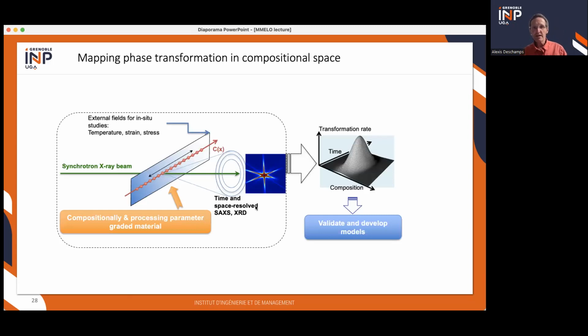The principle is very simple: X-ray experiments are spatially resolved. The classical X-ray beam in a lab experiment is about 1 millimeter. The classical X-ray beam in a synchrotron is about 100 micrometers. Of course, if you want, you can make it smaller, including to sub-micrometer sizes, but it's kind of complicated. They're relatively fast, sometimes below 1 second, and they're in situ. So the idea is just to do them on a gradient and to scan continuously the gradient in front of the X-ray beam to get the transformation rate as a function of time and composition.